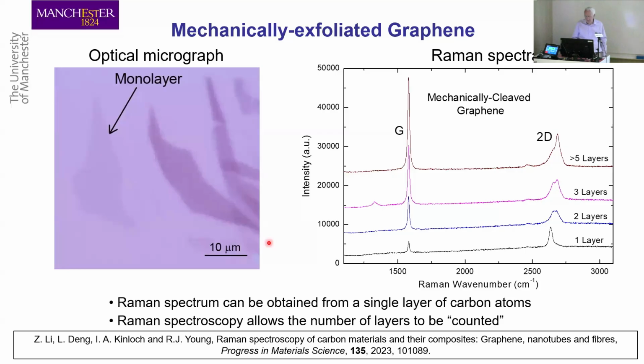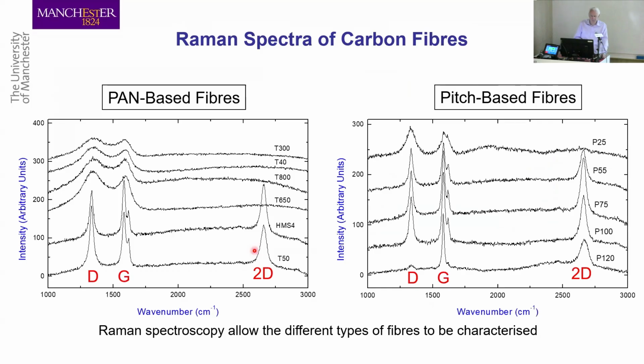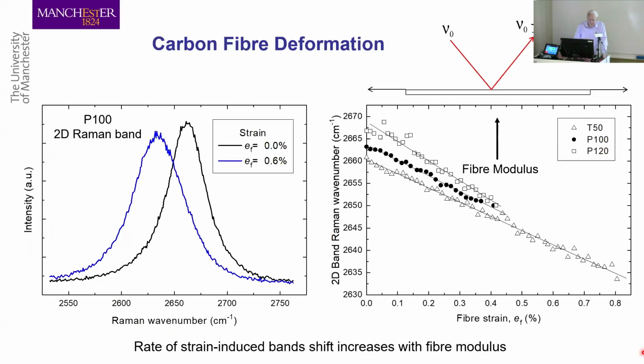You see there's actually a 3rd band here, which is usually quite weak in graphene, but there are these 3 main bands. You see the same bands in the carbon fibers. This is PAN-based carbon fibers, and this is pitch-based carbon fibers. The bands are called D, G, and 2D: G for graphite, D for defects, and 2D for overtones. And you have all these bands in carbon fibers. And what we discovered in the 1980s was if you stretch a carbon fiber and you look at the individual bands, the bands actually move under stress. So black is the undeformed fiber, and blue is the fiber with just a small strain on it. And you get this massive shift in the peak position of the Raman band.